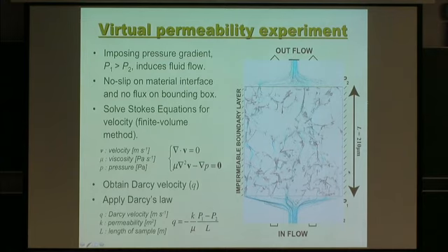All right, so you see now the flow basically goes through that microstructure. You see where the high velocity channels and the low velocity channels are, all right? And with this, obviously, you can also calculate how much the volumetric flux is, and using Darcy's law, you can get the permeability. And obviously, because this is a virtual experiment, you can give the viscosity of your liking, and so that overcomes some of the actual experiments'